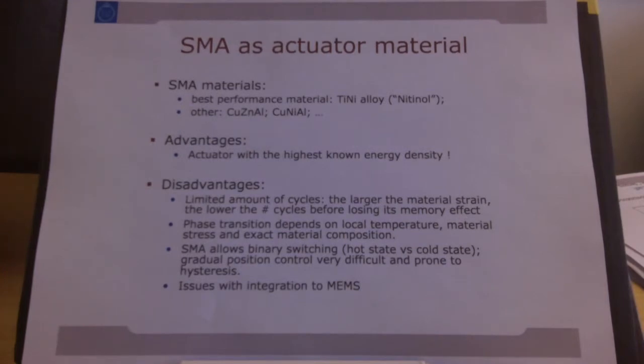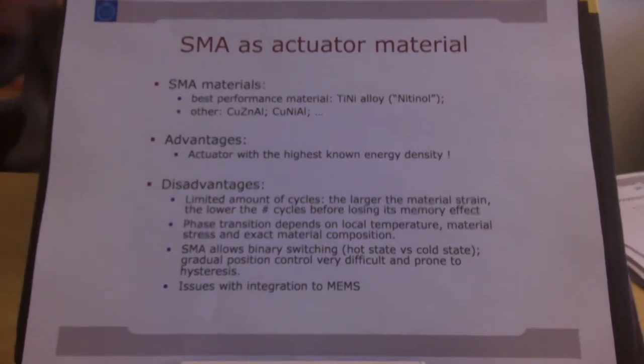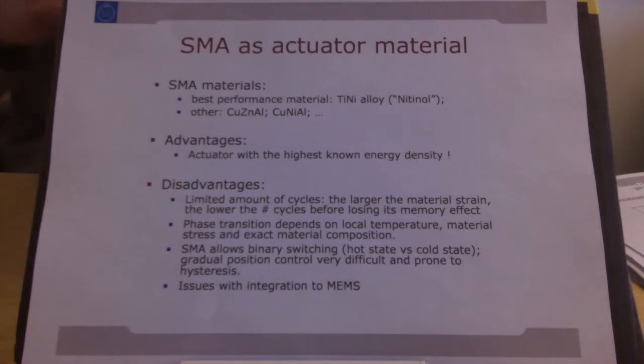There's also cost. It comes at a cost. For one, there is a limitation to the number of cycles you can do before it starts losing, before it starts forgetting its memory state. That number of cycles depends a lot on how much you deform the material. If the local strain is 10% or more, you're going to be limited to maybe a few hundred cycles only. Whereas if the strain is very small, say a percent, you can easily go to hundreds of thousands, maybe 1 million cycles. So the amount of deformation will determine how many cycles you can go with it.